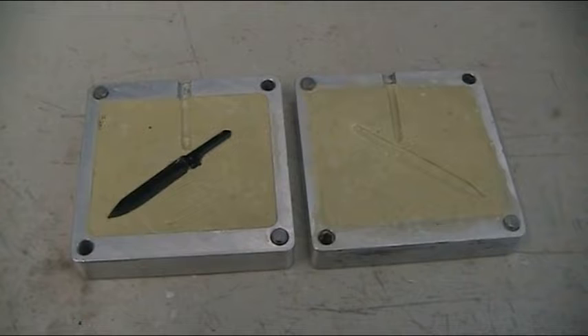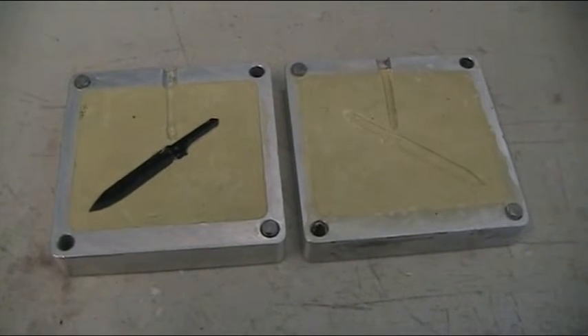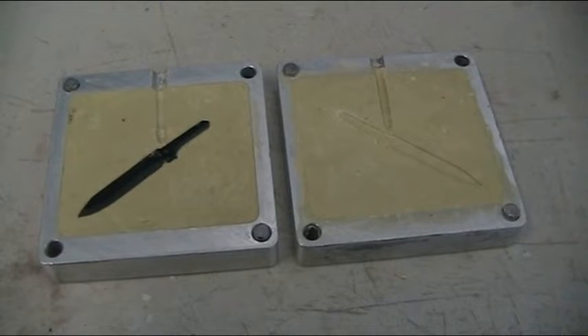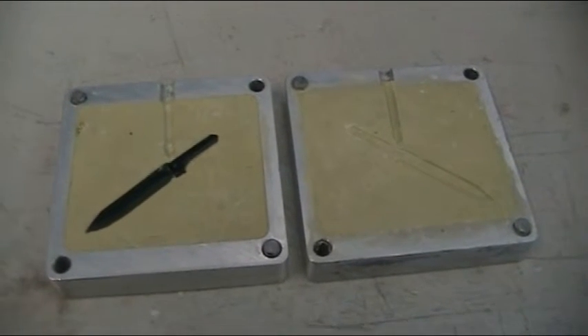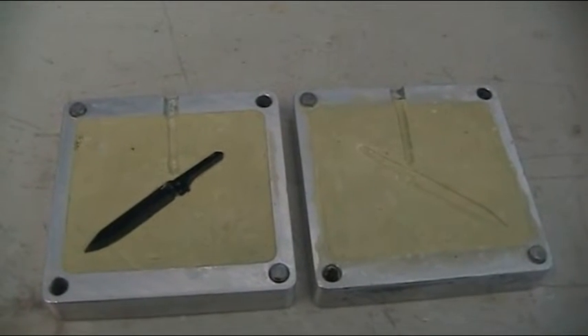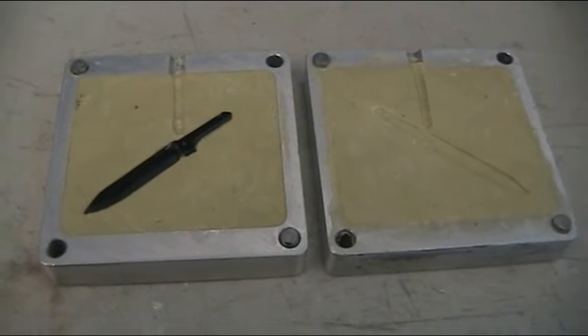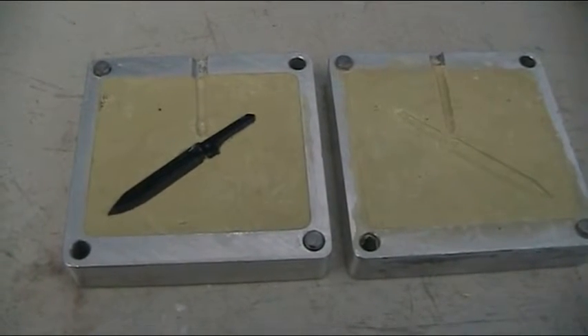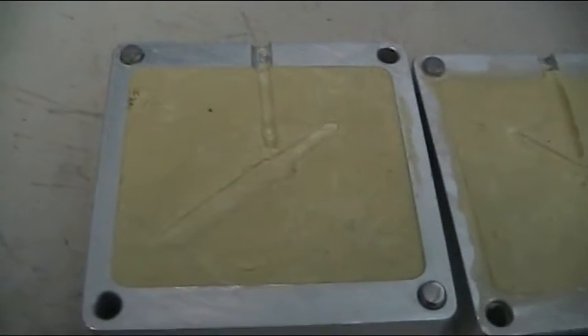We have opened the mold. There have been a couple of issues. The putty is a bit on the soft side. I don't know if it needs more time to dry or what, so we'll just leave it and see how it hardens up. Also, because when I closed it when it was wet, a couple of chunks came off the knife when I pulled it out. So there will be a little bit of detail missing. We'll do an injection and see how we go. We're going to have to try a dry one next time and maybe leave more time for it to chemically firm up.